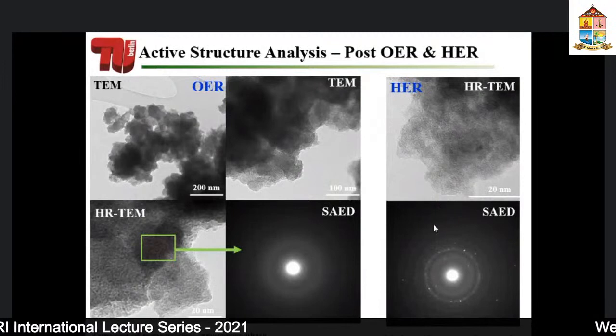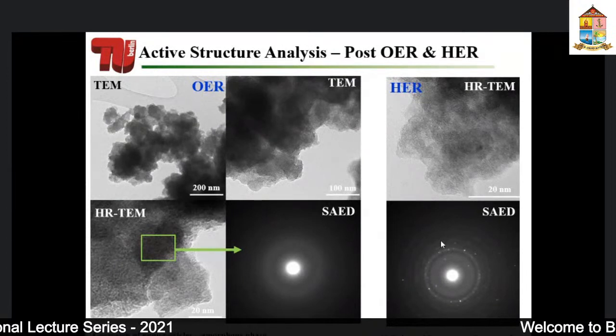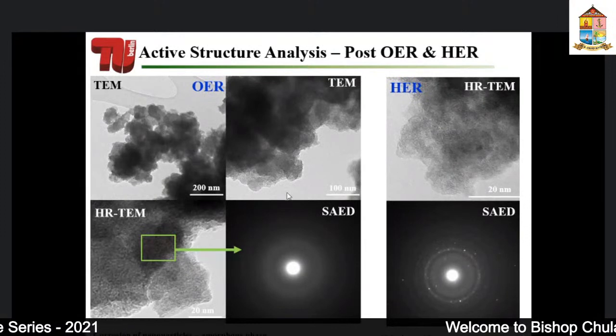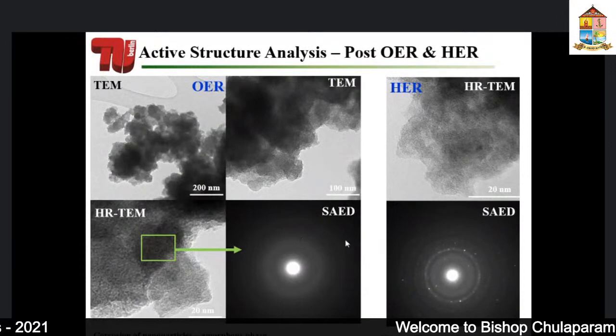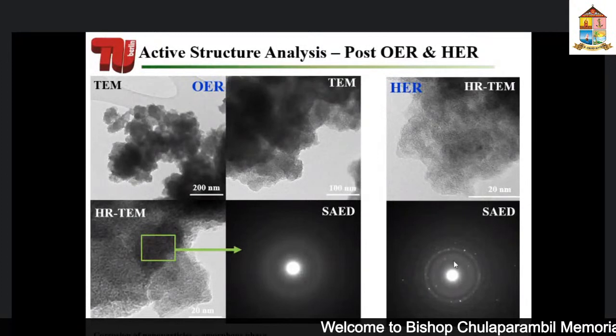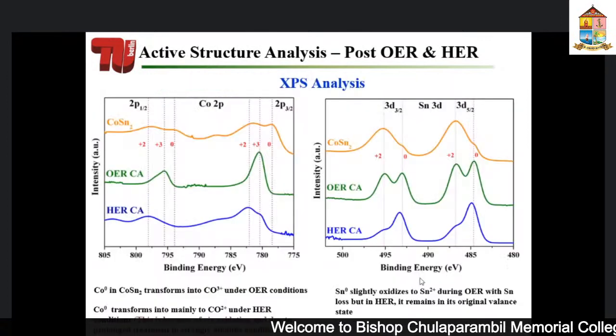So as I said, I will tell you again why it's important to understand the active structure of the materials. Interestingly, what you see here is you start with a nanomaterial, and after the oxygen evolution reaction, you completely form an amorphous structure, as you could see from this pattern, right? No spots. But in the case of the hydrogen evolution reaction, if you look at it after the reaction, what you see is still spots, which means that the material has not changed so much.